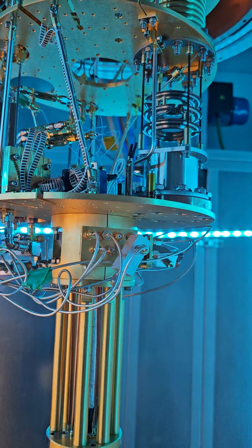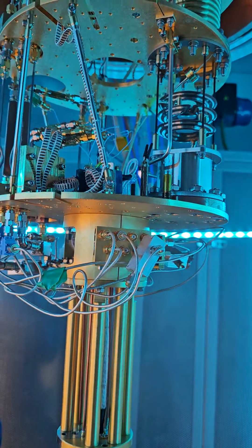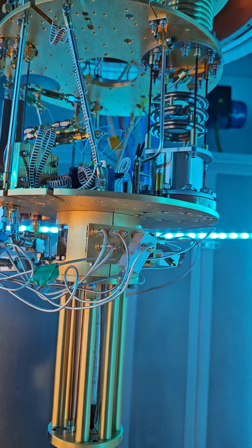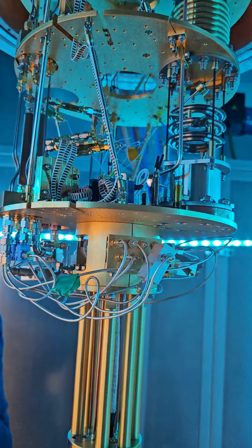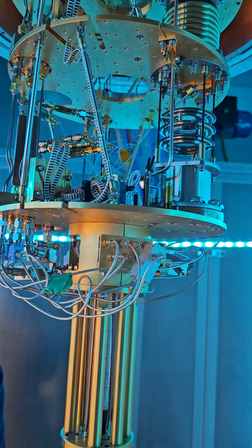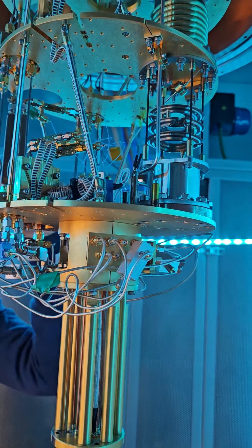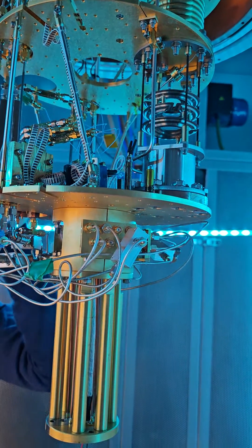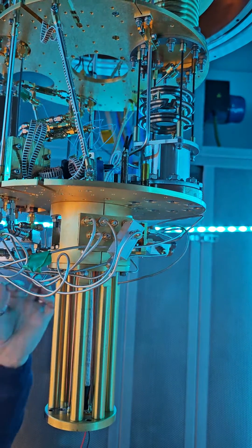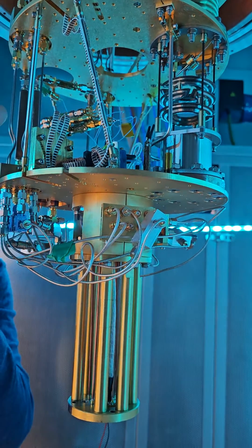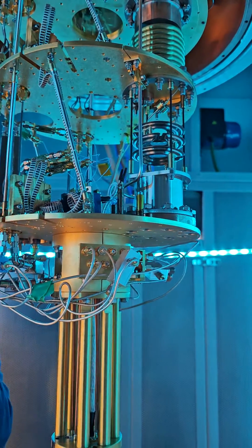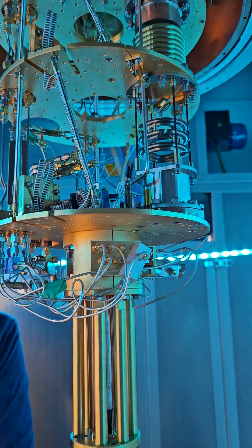When he cooled down the fridge, it was 300 ohms. Like how the hell can it be 300 ohms? And Oxford, we were like, Oxford you've screwed up the looms, and like no, it must be the wiring on your switch. So we dropped all the cans and did a whole test where we short-circuited the micro D connectors together with just a solder joint and cooled it down. It was still 300 ohms.